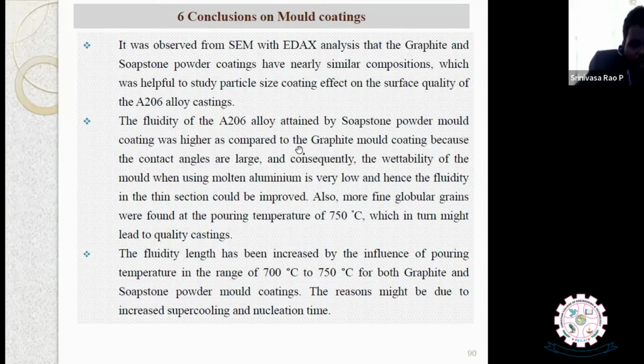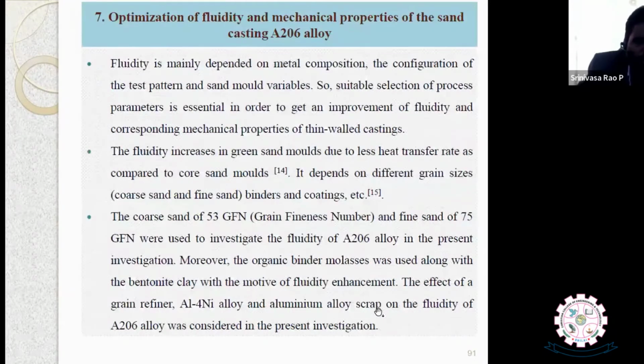And also the A206 alloy fluidity with the soapstone mold was higher as compared to the graphite mold coating, because the contact angles are large. Consequently, the wettability of the mold by molten aluminum is very low, and hence the fluidity in the thin cross section should be improved. So more globular grains are obtained at 750 degrees centigrade. So the fluidity length has been increased by the influence of pouring temperature in the range of 700 to 750 degrees centigrade for both the graphite and soapstone powder molds. The reason might be due to increased supercooling and nucleation.